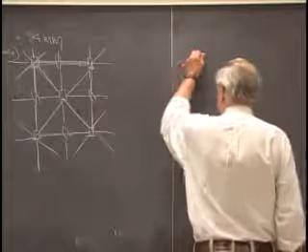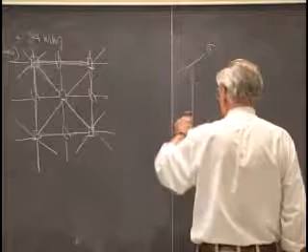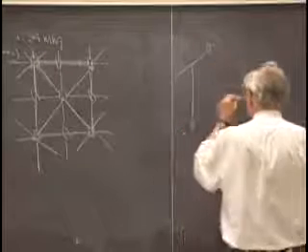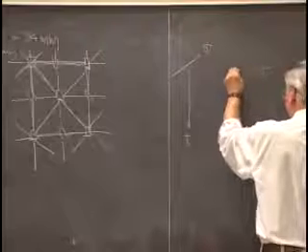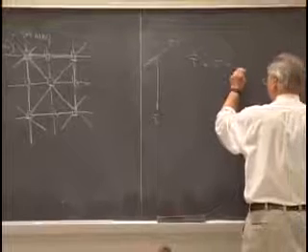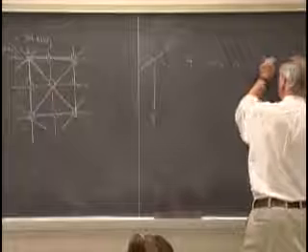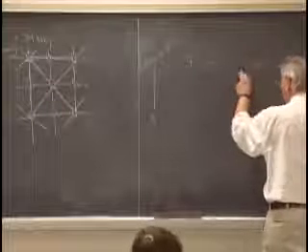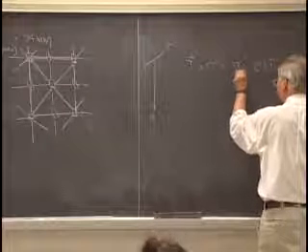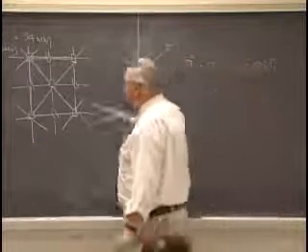So what is that going to require? Here is the mirror plane, that's the operation sigma. And here is our translation, T1, down to here. We have a theorem that says that a reflection followed by a translation that has a general orientation is going to give me a new reflection operation, sigma prime, that's located at 1/2 the perpendicular part of the translation. And it's going to have a glide component that is equal to 1/2 of the parallel part of the translation. So what has that told us?